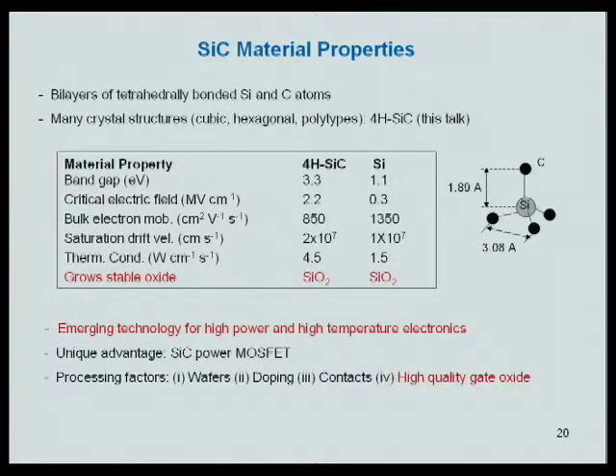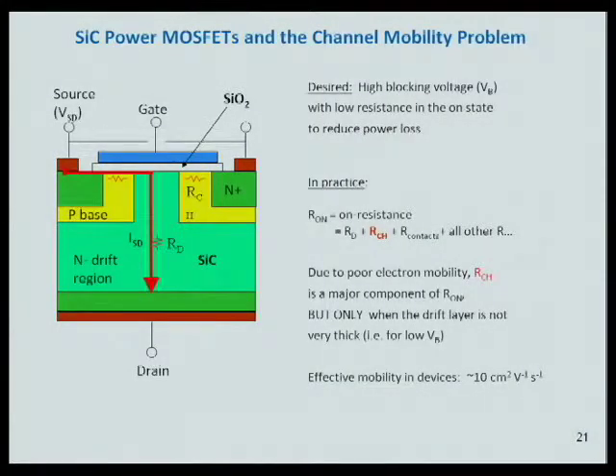And because it's not in some ways so different from silicon, wafers are available, it's easy to dope, people have learned how to make contacts, and we have this high quality gate oxide. Now this is a silicon carbide power MOSFET, and the problem we're interested in is the problem of channel mobility. The effective mobility measured in devices is about 10 centimeters squared per volt second, compared to 850 in a bulk crystal. So something's happening.